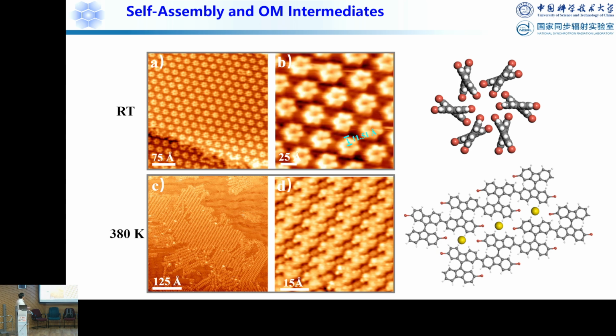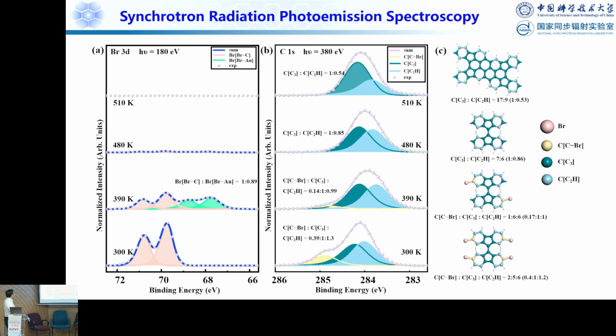Here at low temperature the molecule is self-assembled into this structure, but if you go to 380 Kelvin, this asymmetric Ullmann coupling happens. The asymmetric debromination reaction happens, and now in between they have this gold atom here. You can see it clearly, and this was also proved by synchrotron radiation photoemission spectroscopy, which I will show later. Here at 390 Kelvin, nearly half of the molecules are debrominated because this asymmetric debromination reaction happened.